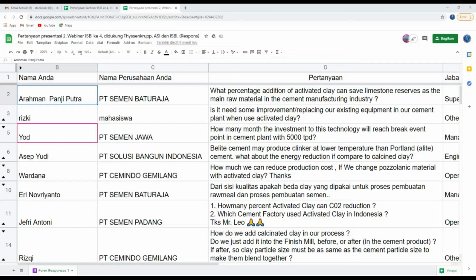If today there's also some limestone used in the mix, which is the case in Indonesia, as well as some other pozzolanic material, then compared to this composition of PPC, it will not be 40%, but lower, something like maybe 20%. But compared to OPC, you will save around 40% when using LC3 cement.